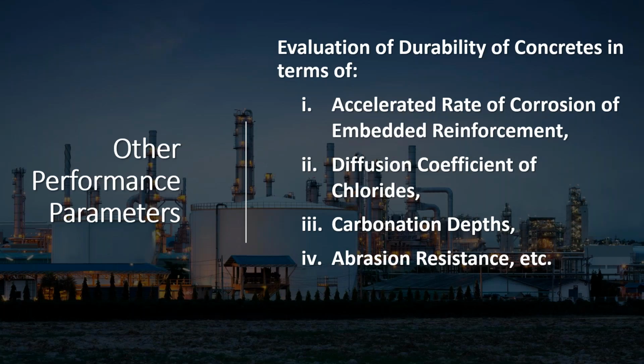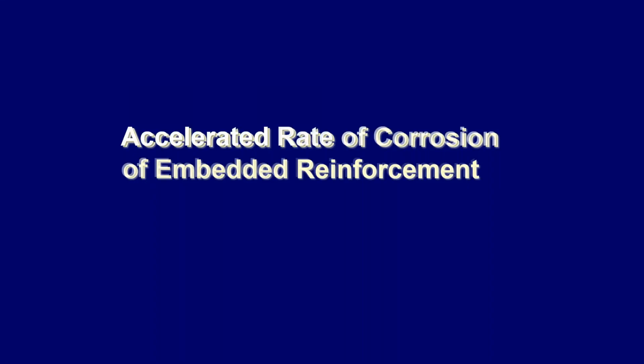Now, what are the other performance parameters? Because RCPT is not the only thing. Coulombs is not the only thing. There are other performance parameters. Accelerated rate of corrosion of embedded reinforcement. That means you can measure the rate of corrosion for different concretes under accelerated condition and express that rate of corrosion as the performance of that concrete, and also you can classify the performance in terms of the percentage of the corrosion rate. One more relation could be the diffusion coefficient of chlorides. You can measure the diffusion coefficient for different concretes and express it as the performance parameter, and also carbonation depths and abrasion resistance. I have done some work in this area.